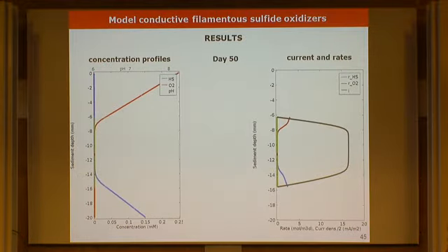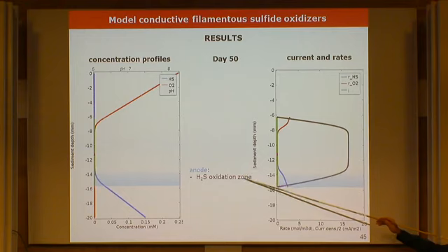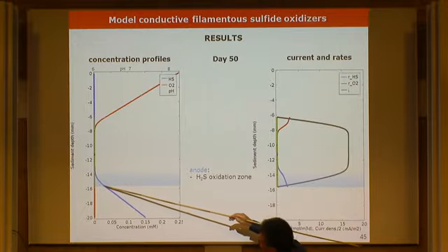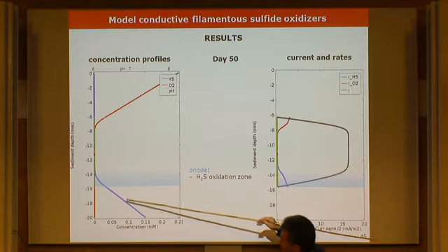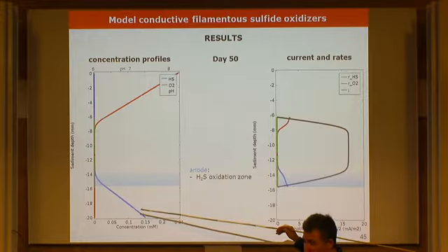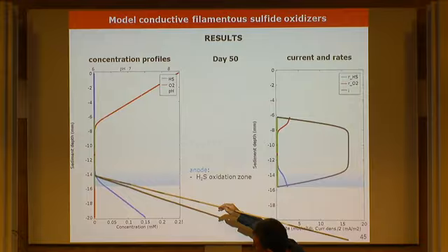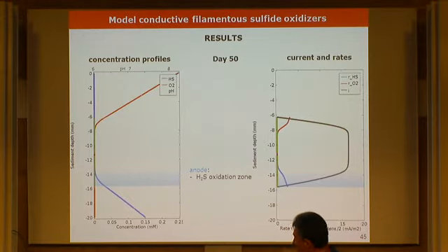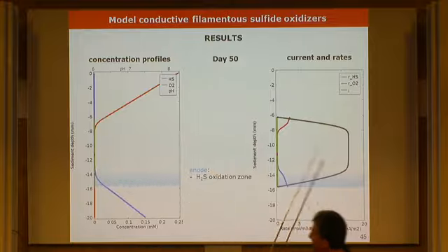Okay, these are the typical profiles obtained with the simulations. Here you have concentration profiles, and here you have the current in black, electrical current, and these are the catabolic rates. Red is oxygen reduction, blue is sulfide oxidation. So practically what you see here is that you have a sulfide oxidation zone here, where you have this reaction, and this also corresponds to this bend in the sulfide profile. Sulfide is only diffusing here. That's why it's a straight profile, probably you know this. It's just diffusion. But here where it bends, you have consumption. And there is nothing left here.